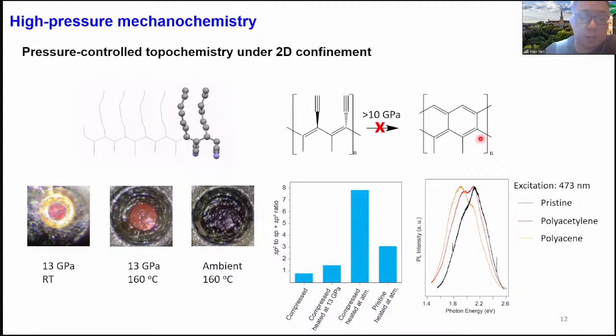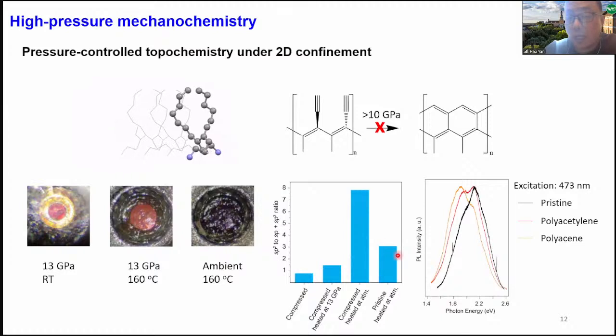Now, also interesting here is that if we just take the pristine material and heat it directly at room temperature, at room ambient pressure, we see that the product is likely a mixture of the polyacetylene and polyacene. In other words, by using pressure, we're encoding a unique selectivity in this reaction.